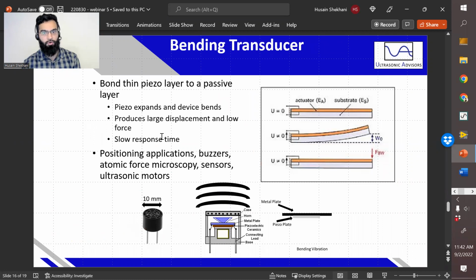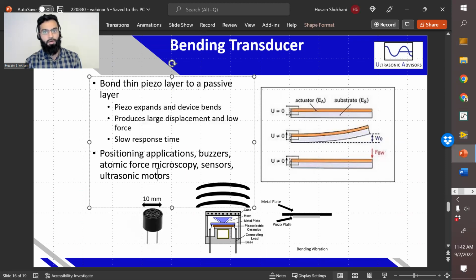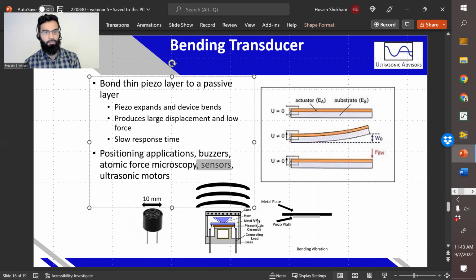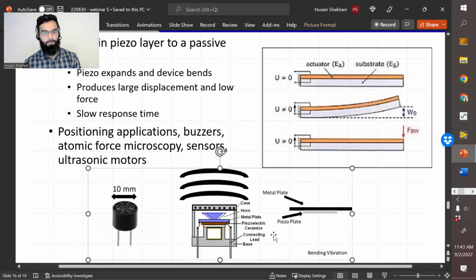Here's a bending transducer. In order to get that 0.4 microns to do something for you, you bond a thin layer to a passive layer, and as the piezo expands, the device bends in different ways depending on the polarity of your voltage. This produces large displacement and low force. It has a slow response time, but they are very useful in many applications, like buzzers and all this type of device. And there are some very high-tech devices like atomic force microscopy, which uses that.